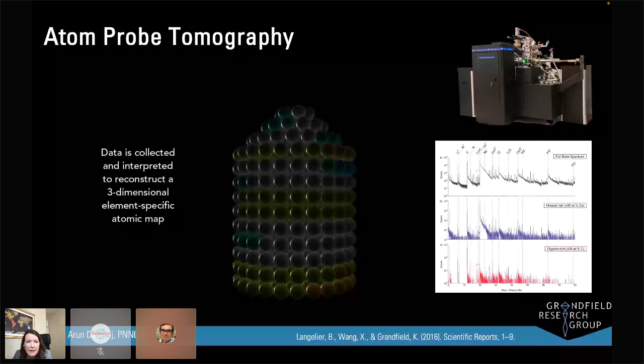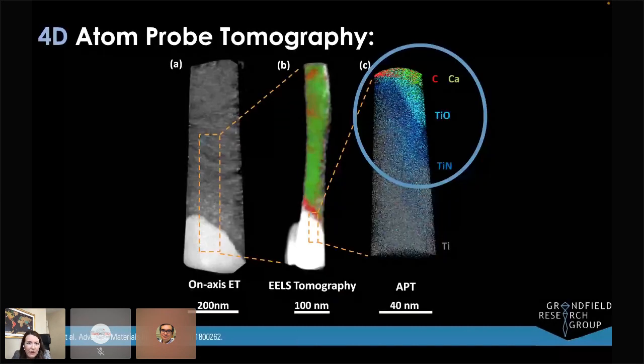When we take our same sample that we did electron tomography and EELS tomography on, and place it in the atom probe, we have a very small volume that we collect right at the bone implant interface. Each one of these dots represents a cluster of atoms. We have titanium atoms at the bottom, calcium and carbon atoms at the top representing our bone mineral, and then a layer showing our oxide from the laser ablation.